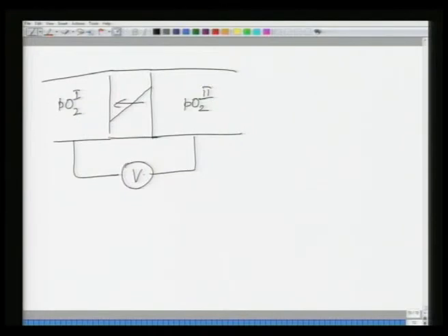Now, when you have an electrical signal as a result of this ionic concentration gradient, you must not have electronic conduction, otherwise you will have short circuiting. So, for these kinds of applications one must ensure that Ti is equal to 1, which means Te is negligible, no electronic conduction. You would prefer a system where ionic conductivity is highest to avoid short circuiting. So, consider now two sides separated by an electrolyte.